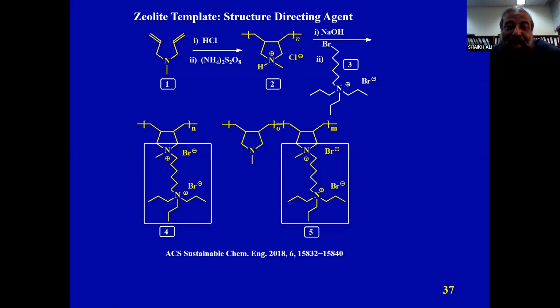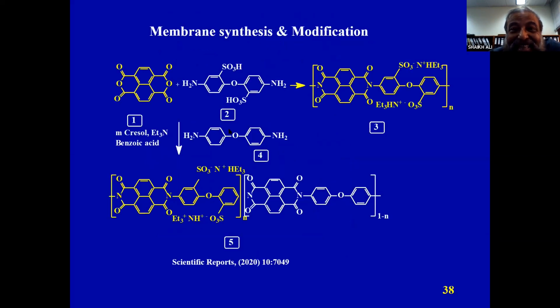Now here we have also made from cyclopolymerization some zeolite template structure directing agent, and that agent can make certain type of zeolite ZSM-5 with certain pore requirements that can selectively give us cracking of hydrocarbon to propylene. And here we did synthesis for membrane synthesis and modification. Number 3 is a membrane, number 5 is a membrane.